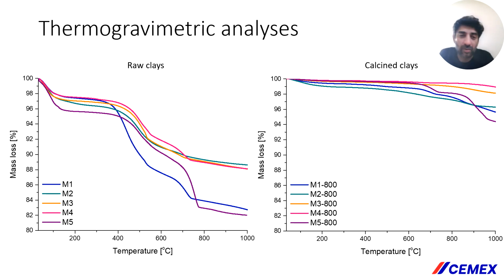But basically, based on these findings from XRD and TGA, the calcining parameters were decided to be 800 degrees Celsius peak temperature for a residence time of 1 hour to drive the dehydroxylation and amorphization of both 1:1 and 2:1 clay minerals, and to fully decompose pyrite, but we wanted to limit the decomposition of carbonates.